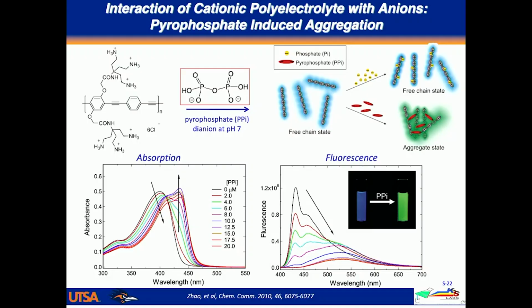Okay, so I showed you this slide before, and I want to show you now how we can make the sensor a little bit more simple. And what I showed you before is this more complicated positively charged polyelectrolyte. And I told you that if you add pyrophosphate to that polymer, you can directly induce aggregation. And now you know from what I told you previously that if we add alkaline phosphatase to a solution of pyrophosphate, it's going to break the pyrophosphate down into monophosphate. So if this reaction that I'm showing here, that is the aggregation, can be reversed, we can take advantage of the reversal of the aggregation to measure the hydrolysis of PPi by an enzyme.